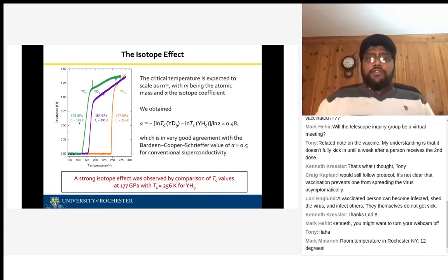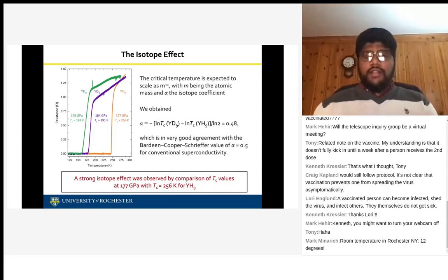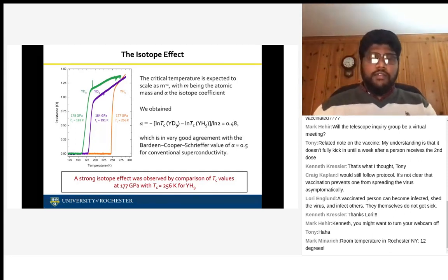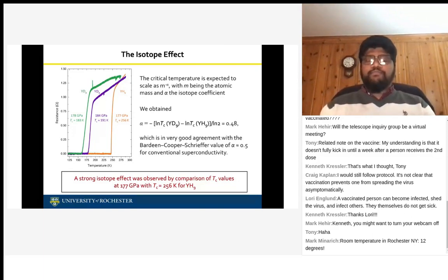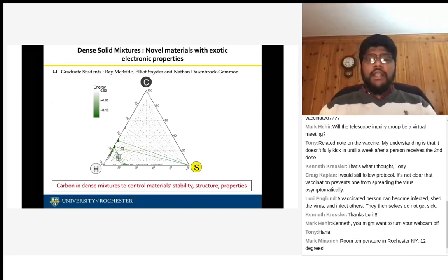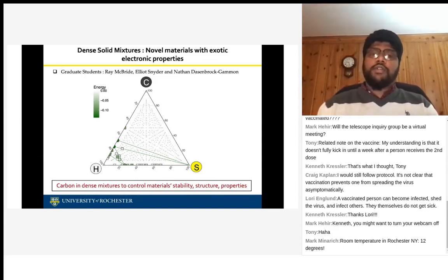So this was great. We found a superconductor almost at room temperature, almost close to the freezing point of water. But we were not really satisfied. So we started thinking, what are the other ways that we can make a stable superconducting material? We started going in the direction that carbon can play an important role here, because carbon has the property of making highly covalent bonded material, with fourfold or maybe even sixfold carbon, which can have a very strong lattice, and which means that you can have a very strong electron-phonon coupling.